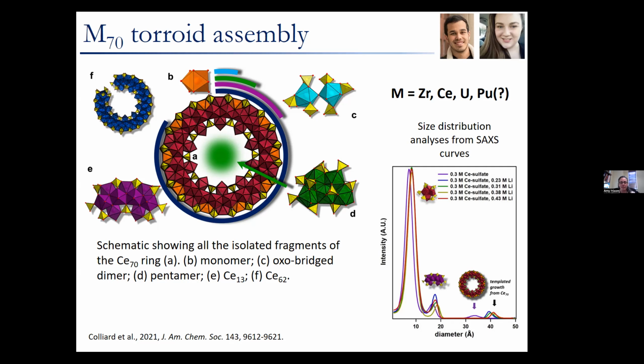Ian Colliard out of Oregon State was able to use both single crystal X-ray diffraction and small angle X-ray scattering to understand what the formation pathway was. So the toroid itself, we have this M70 ring, which is the dark red polyhedra, in this case for cerium. And then there are decorations on the outside and the inside of the toroid with just the monomer, the cerium monomer that's bridged by sulfates.